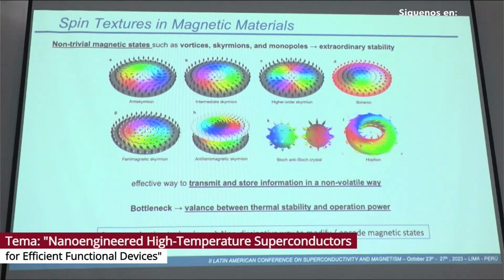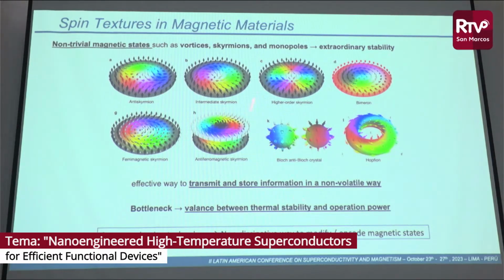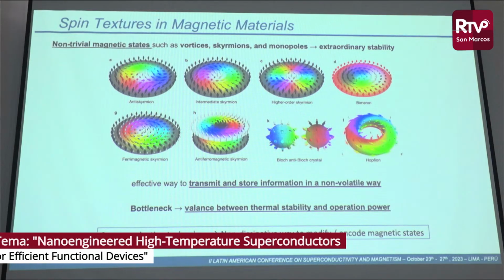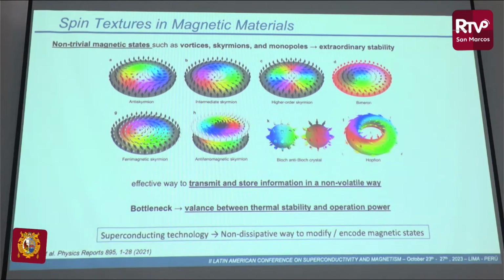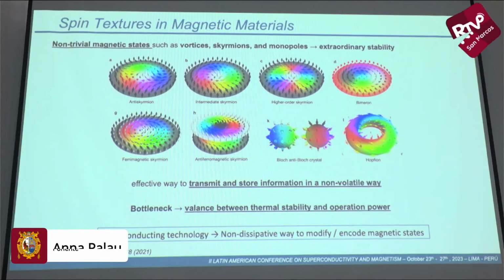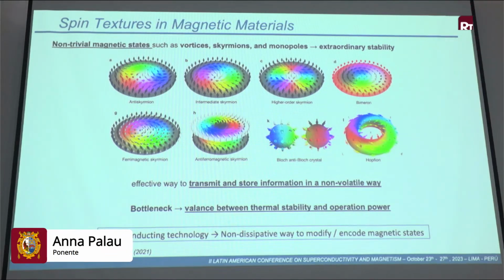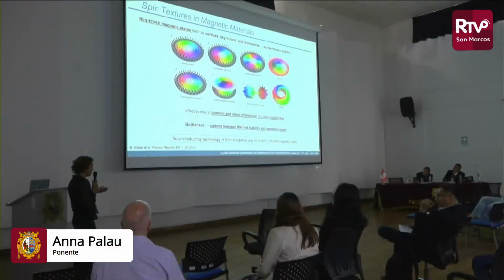And the main bottleneck playing with these materials is the fact that very stable systems need to be worked with large currents, for example, and the bottleneck in these systems is the balance between the thermal stability of the system and the operation power that one needs to operate with these systems. Superconductivity may be key in this problem, because in a superconductor we can pass current through the system and stabilize magnetic fields without any need of energy.